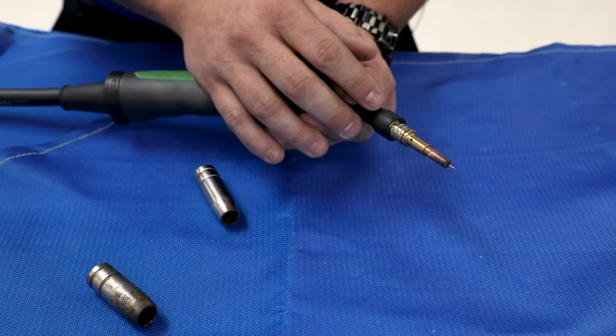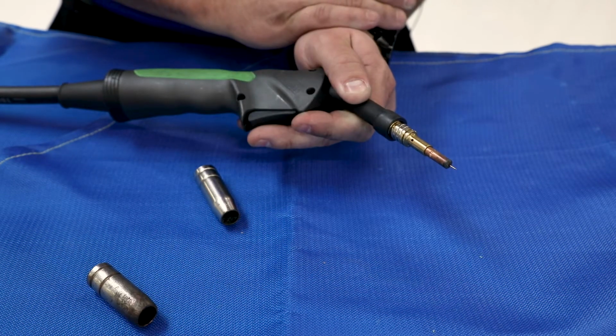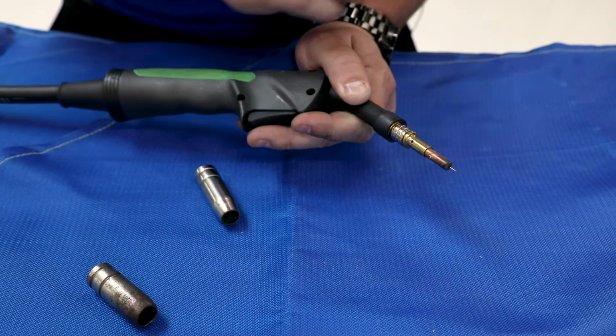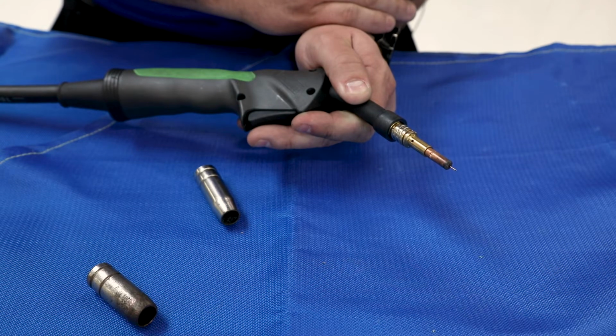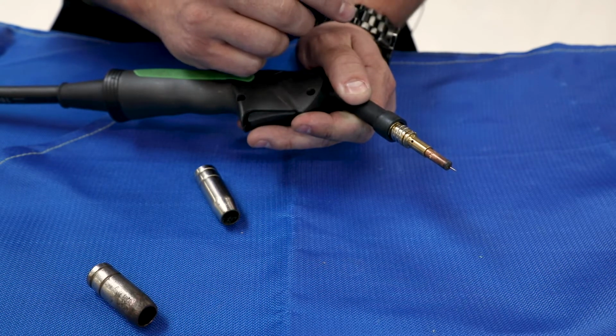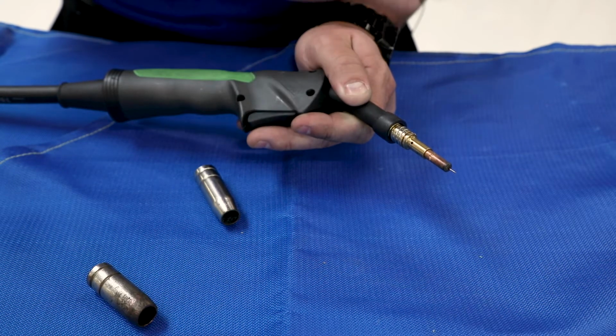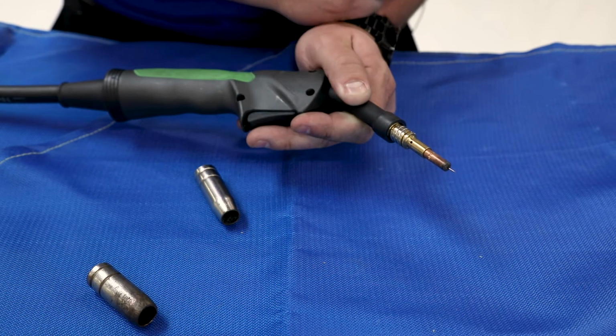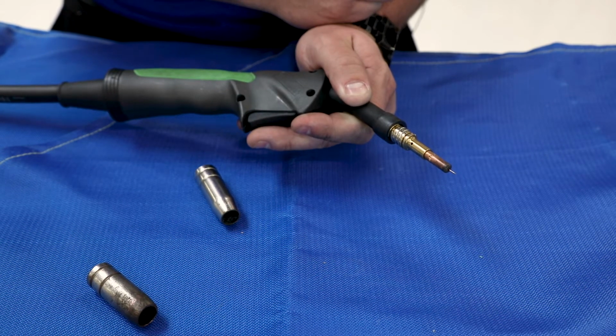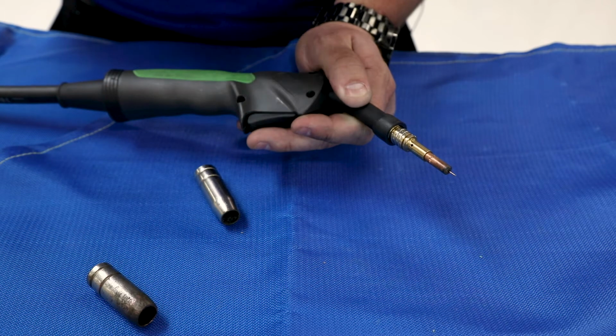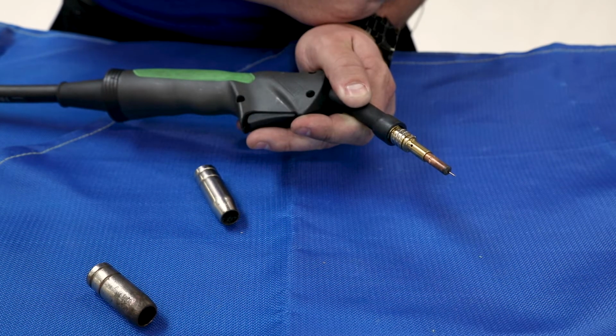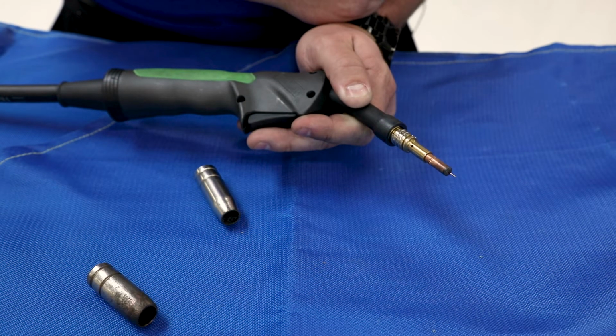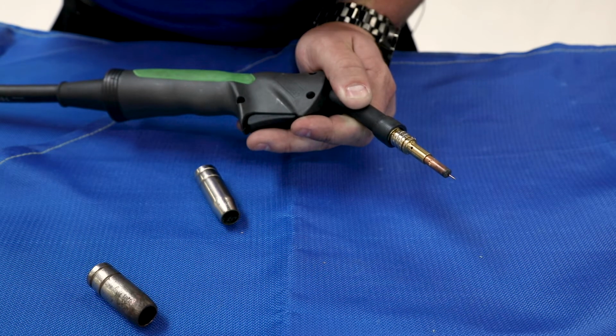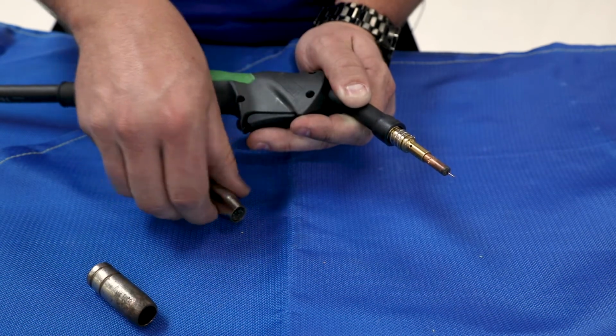We want to also make sure that we don't forget to put the gas diffuser on. The contact tip and the gas diffuser have the same threads. So it is possible to screw the contact tip directly into the torch neck and forget the gas diffuser altogether. When this happens, the torch will not allow the gas to flow out, and we will have a very dirty and poppy weld with a lot of porosity. So it's important to make sure that we put that contact tip and the gas diffuser back in there together.